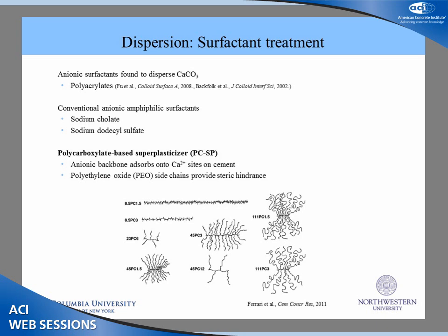And these are anionic, consisting of an anionic backbone that's designed to absorb onto the calcium sites of cement, and also has polyethylene oxide side chains that provide steric hindrance. So PC superplasticizers are systematically used in concrete. So the benefit was that we would expect no incompatibilities within our system. And also there's the flexibility of altering its architecture, so you can change the number of repeatable units in the backbone, and also the length of the side chains.